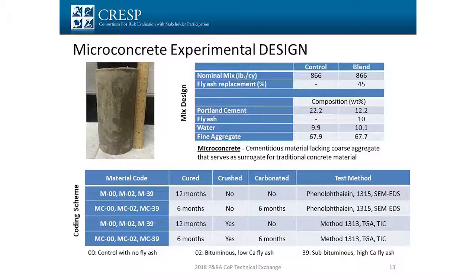So what we did was develop a series of what we call microconcretes. I should say Janelle Branch, a former PhD student, developed them. I think we've actually called those sieve concretes now, where the idea is you take the surface area you would get from the small aggregate and the large aggregate, and you conserve that surface area, and you'll see the leaching properties work about the same as if you still had the large aggregate in. So it's a good surrogate for a vault material if you're going to do things like small-scale SEM and other analyses, which is what we're doing.